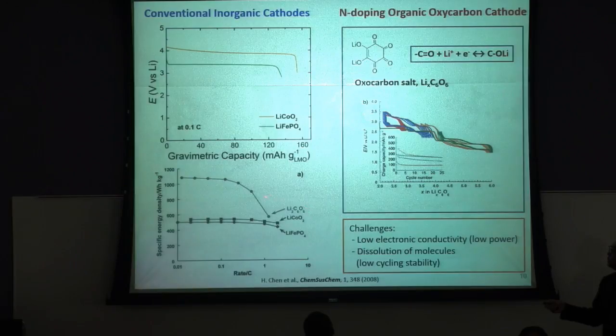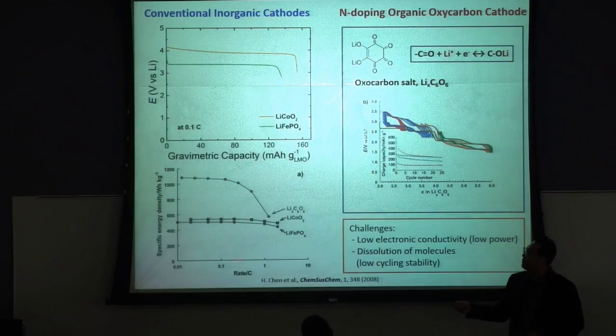So if we compare this organic molecule with the inorganic cathode, you can see the energy density is more than 2 times. But there are critical challenges with this kind of organic material. The first one is that this organic material is insulating, right? So basically, their power performance or rate performance is limited. If we increase the charging discharging rate, their performance quickly decreases.